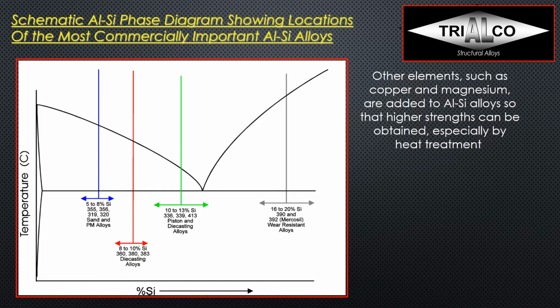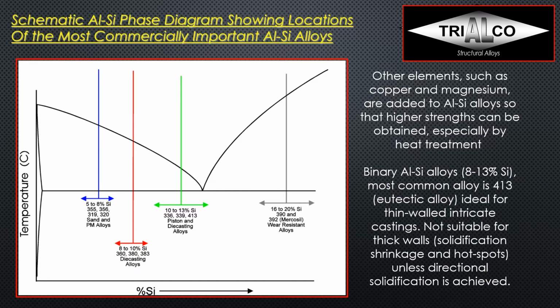And then between 10 and 13% silicon, we find the close to eutectic alloys, so that would be the 336, 339, and of course the 413, which is pretty much a eutectic alloy. So we find piston and some die casting alloys. And then we have pretty much nothing until we get to far hyper-eutectic, so in the range of 16 to 20% silicon, and that's where we have the 390 type alloy with some variants like the 392, the Mercosil. They are used for high wear resistance.